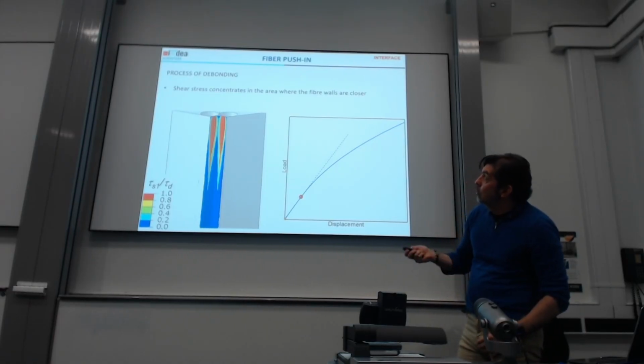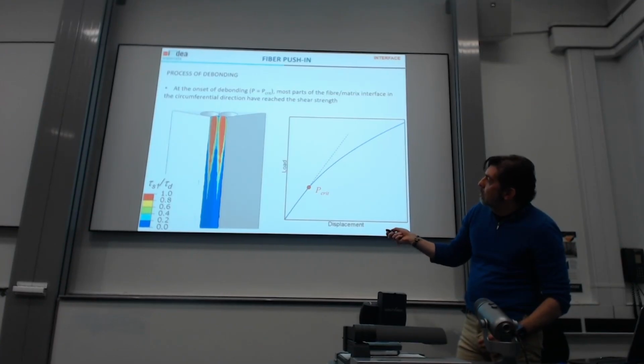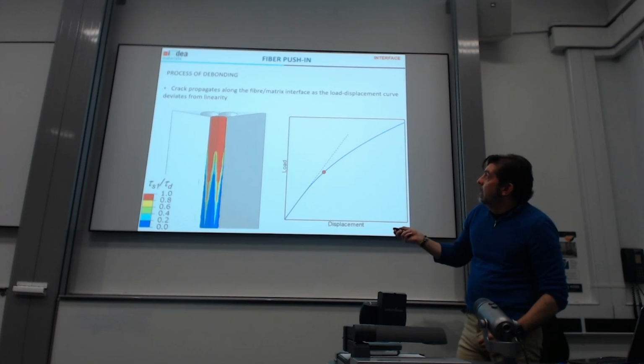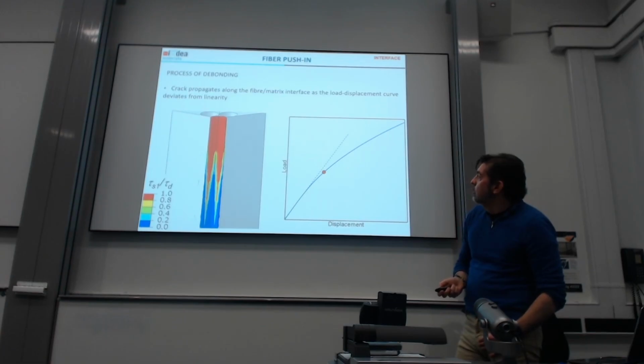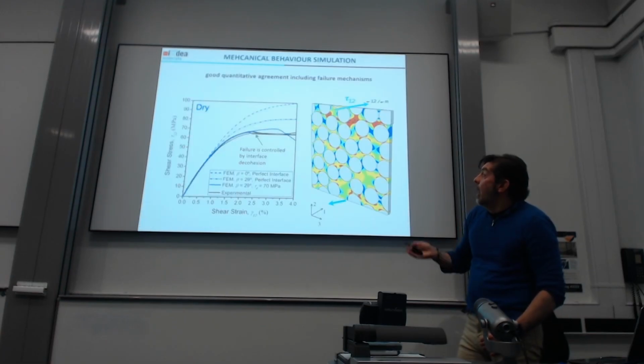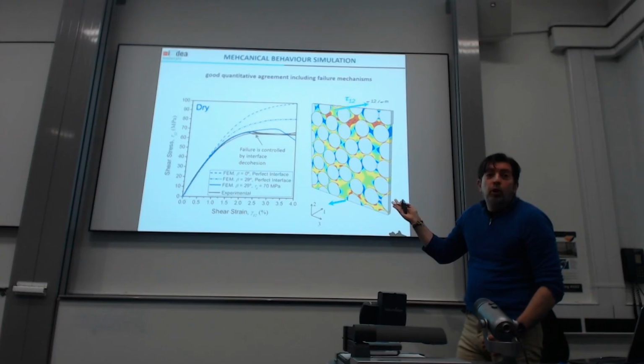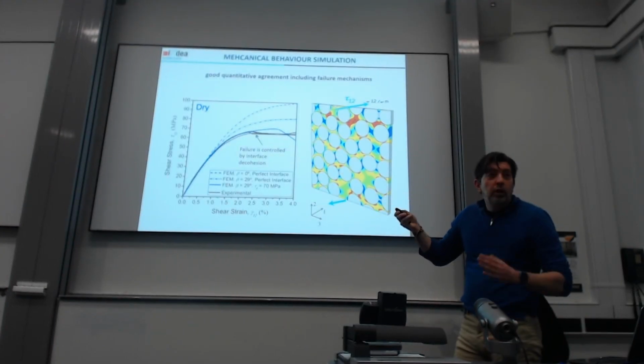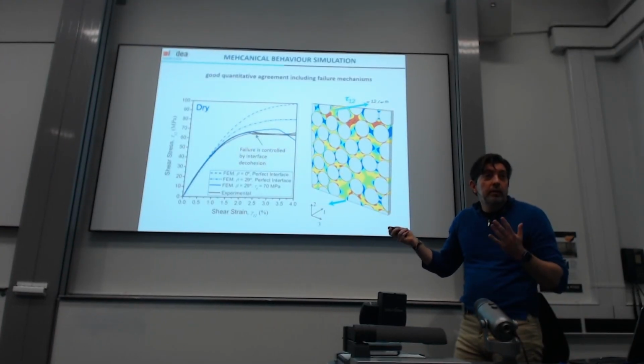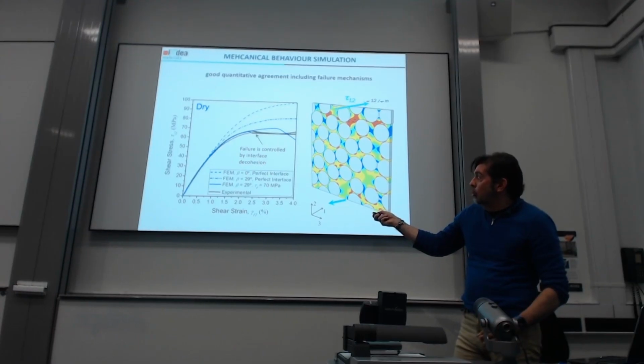So the shear stress concentrates at the fibers, and then when we reach the critical load, most of the interface is debonded, and then we have the crack go down into the sample. And the take-home message is that you cannot assume a perfect interface. Sometimes the interface is controlling the failure of the composite material.